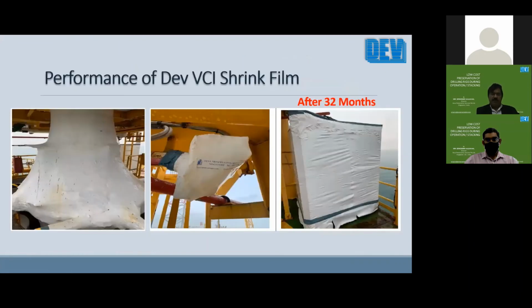And this is a recent example from one of our clients, which we had preserved about 32 months earlier, in Southeast Asia. The shrink film is still in good intact condition. Even though it is warranted for 12 months, it has performed up to 32 months because in this area the UV radiation was less, so the damage due to UV is lesser.